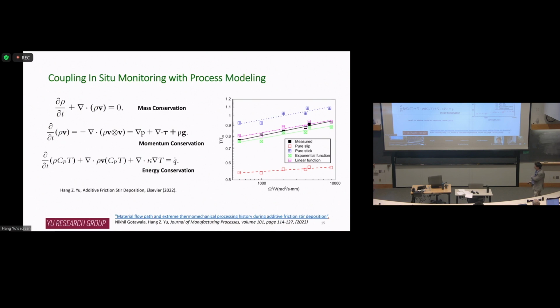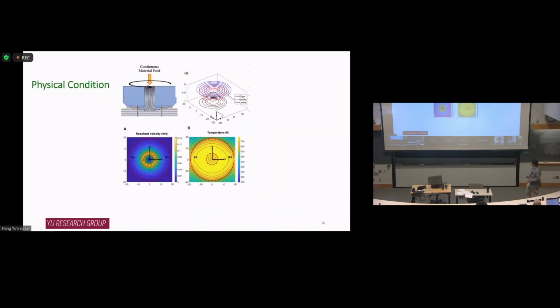So basically, the three key equations are conservation of mass, conservation of momentum, and conservation of energy. So you can predict the steady state temperature and the velocity distribution. And you can validate the prediction with some experiments we have. Once the modeling has been validated, we can get some more insights that cannot be obtained from experiments. One is the material flow path. We conclude that the material goes down, and then you have a kind of spiral-shaped flow path. Along the material flow path, we can record the temperature, because we know the steady state temperature distribution. Now we know the flow path, we can do particle tracking, so we can get a history of the temperature and the history of the strain rate as well.